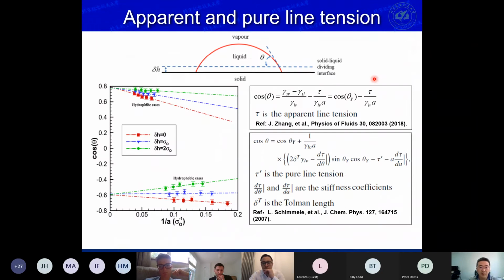And the key point is actually caused by the position of the solid and liquid dividing interface. Because when we measure the contact angle, we need to define where the interface is. Here we use a delta H to define the distance above the topmost of the solid atoms. If delta H is 0, it's just on the solid surface. Here we use 3 different types of definition: delta H equals 0, 1 sigma, or 2 sigma.